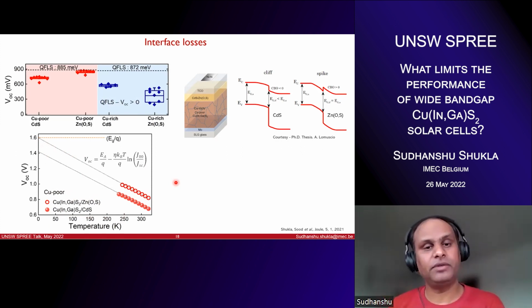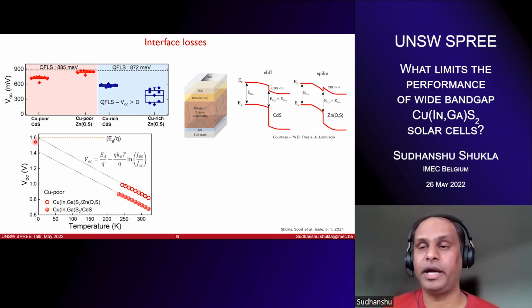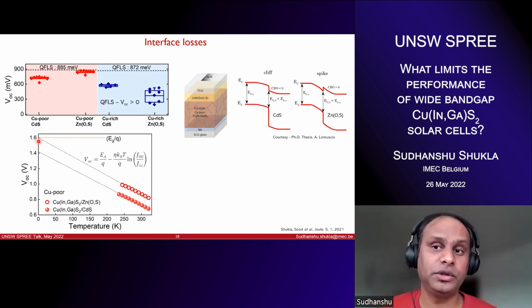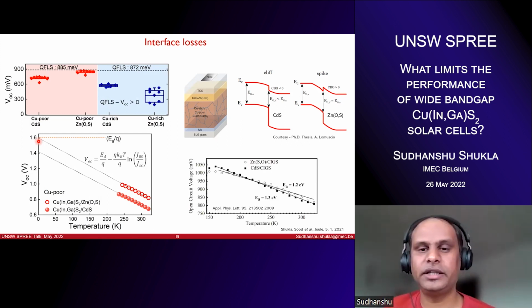So you have to be again very careful when you look at such plots and they go exactly at the band gap. It doesn't mean you have zero interface recombination. It tells you have passivated interface defects and there is less interface recombination, but you cannot conclusively say that you have zero interface recombination. And that is what you look at historically.